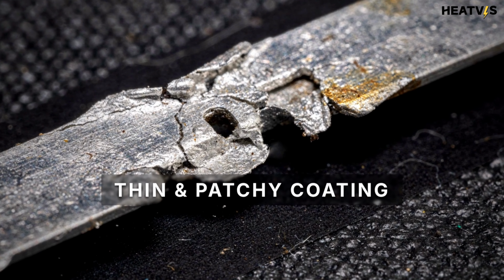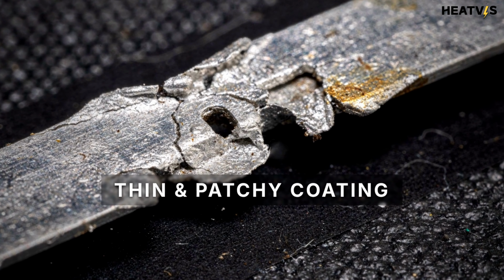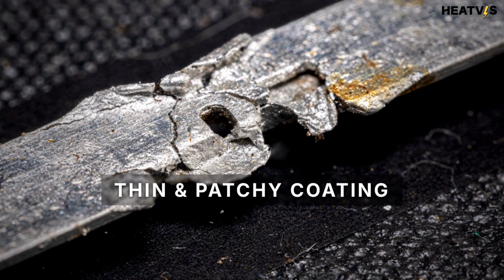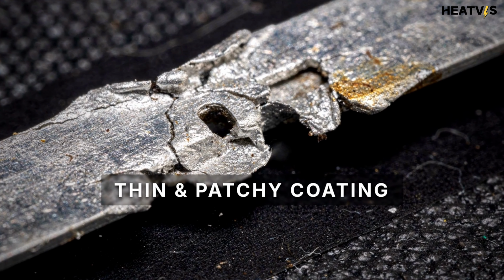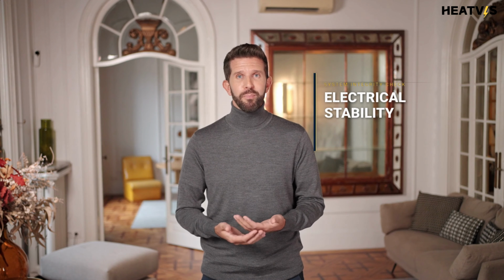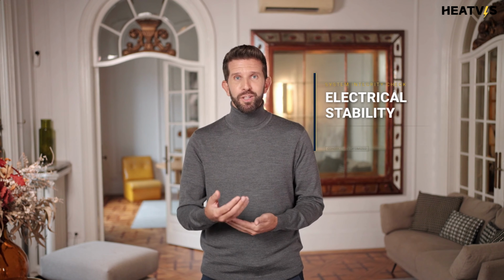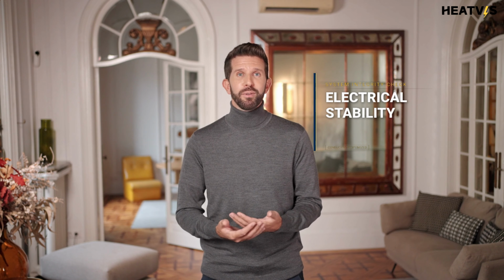In low-cost film, manufacturers often reduce the silver content or use lower-density material, which increases contact resistance. And when contact resistance goes up, two things usually happen. Connector areas overheat and overall output drops. Silver is a major cost driver, but it's also one of the clearest indicators of electrical stability.